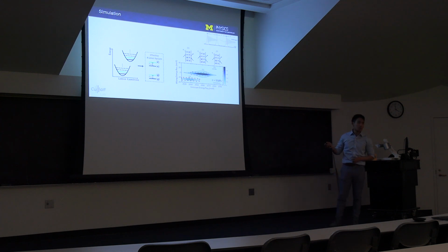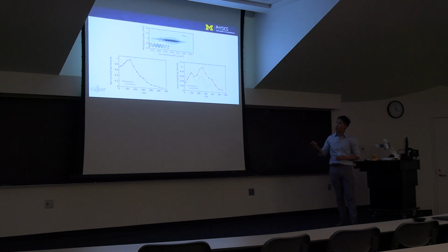So if we look at the quantum pathways that generate the peaks in our zero quantum spectra, we see that the sideband is predominantly generated by pathways of initial interband coherences involving a vibrationally excited state. So in a way, our zero quantum spectra tags the dynamics of the vibrationally excited interband coherences by isolating them in the sideband. But unfortunately, we weren't able to reproduce the long rise that we saw in experiment.